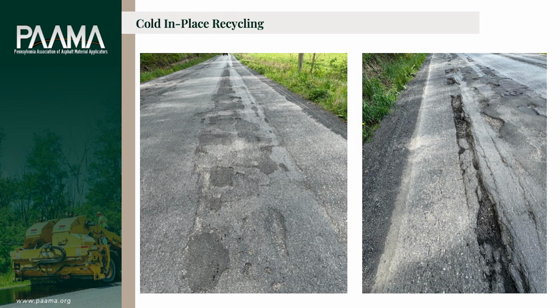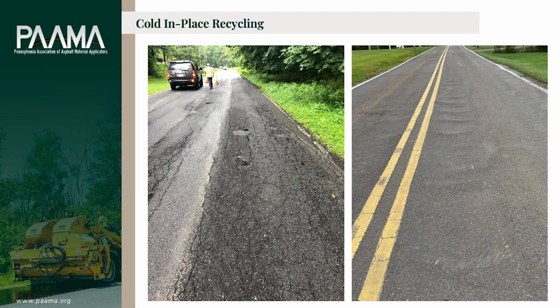It's been patched several times. You've got, it looks like, some widening going on at the edges of the road. You've got those cracks all over the place. Here we've got a lot of raveling going on. We've got widened areas where the joint of the old pavement and the widened area have broken apart. Another typical section here, corrugation, you've got patch on top of patch. And in the photograph to the right is where a very soft asphalt has been applied and you've got those rumble strips being created.